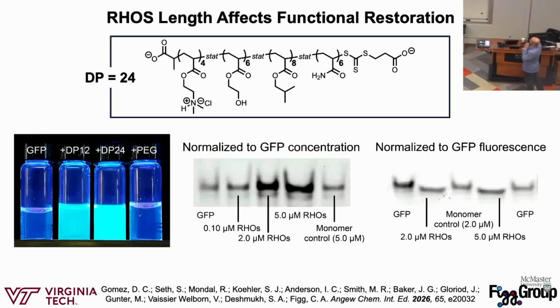I like pictures. So this is a picture making sure that it's not just due to molecular crowding for this fluorescence increase. This is GFP under UV light. So GFP just looks like that. We added in a polyethylene glycol control of the same molecular weight and same concentration just to make sure it's not crowding. And then as you add in your DPs, you see a very visual difference in fluorescence. Depending on the projector, you can see that the DP24 is maybe a bit brighter than the DP12. So even an effect of the length, you're seeing in the brightness of the GFP, and it's very visual that the GFP fluorescence is changing even on the benchtop.